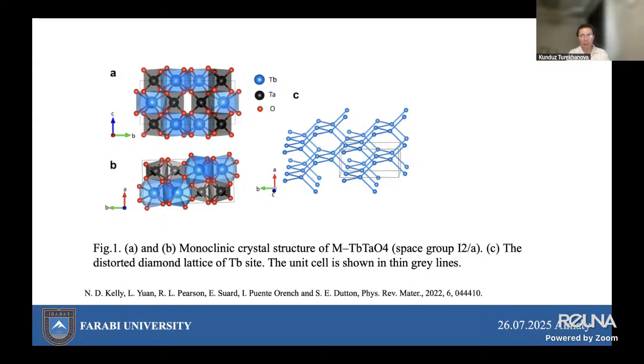All the data given in this presentation was obtained experimentally in the Cavendish Laboratory. The polycrystalline terbium tantalate was synthesized according to the solid-state ceramic reaction, as has been reported elsewhere. 50-50 molar amounts of the reagents were thoroughly mixed in an agate pestle and mortar and pressed into a pellet, maybe 6 or 7 millimeters in size, and placed in an aluminum crucible.